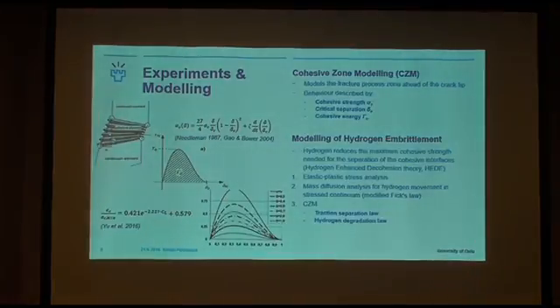And then cohesive zone modeling is a technique that models the fracture process zone ahead of the crack tip. It's implemented in conventional continuum models by inserting cohesive elements on the anticipated crack path. The behavior of these elements can be described by this traction separation law, which consists of a cohesive critical strength at the maximum level of the critical separation, and the damage is accumulated under the curve.